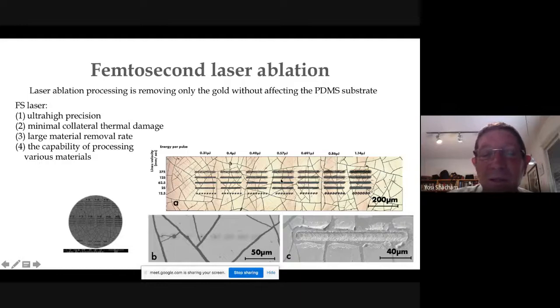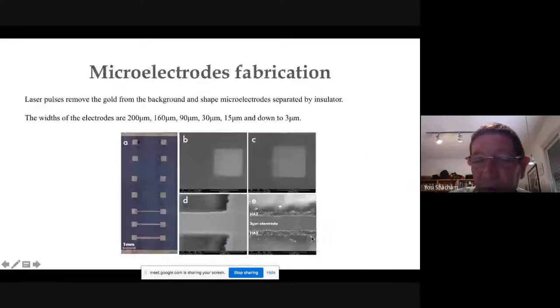By the way, you can see here that we used the monomer and the PDMS with a relatively high CTE, so we got cracks. But the good news is that even though we have cracks, all the devices worked, because the cracks are only in the gold on top of the PDMS. The gold inside the PDMS is still conducting. This is the top view, this is the cross section.